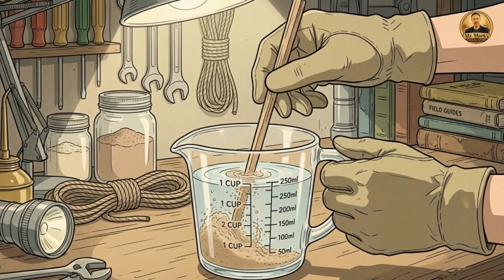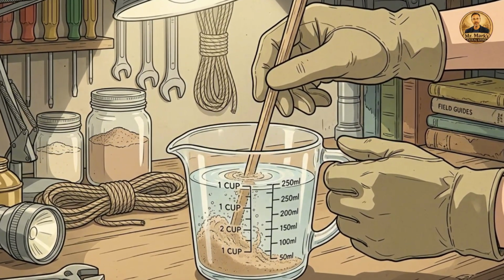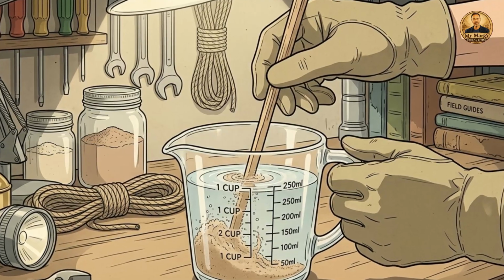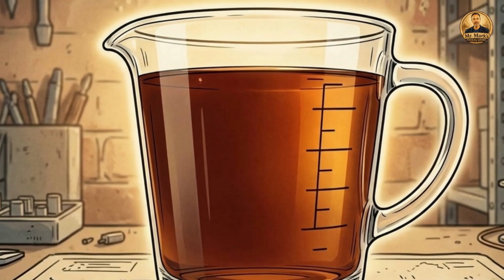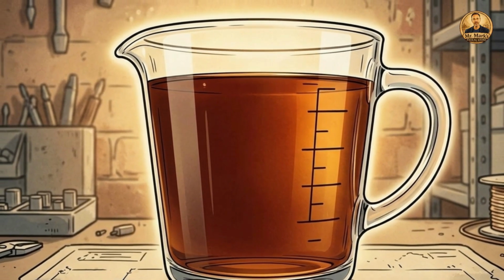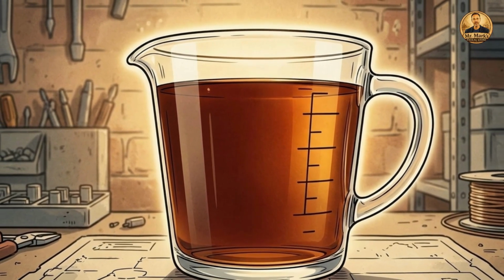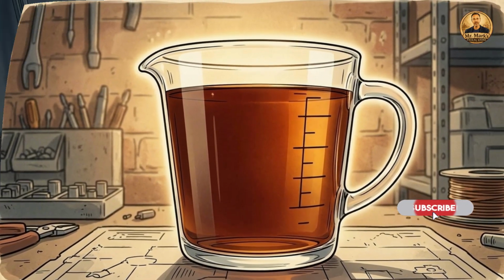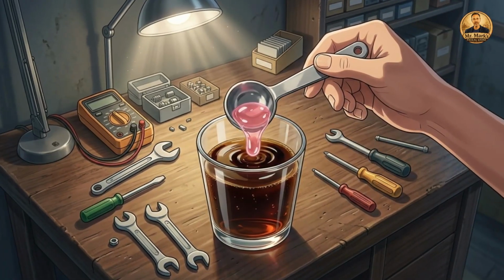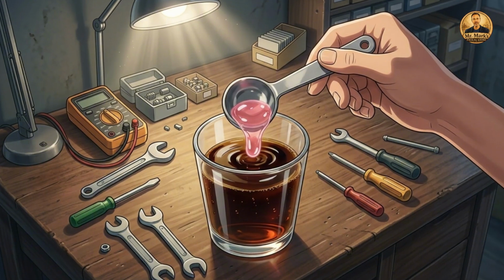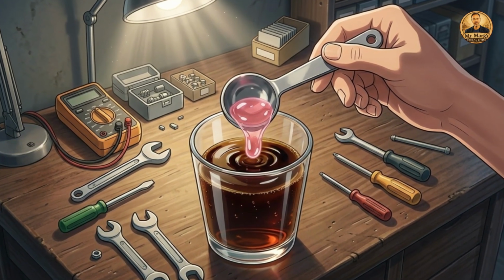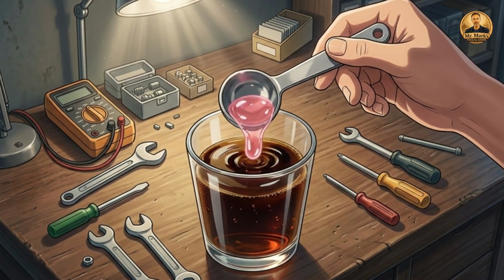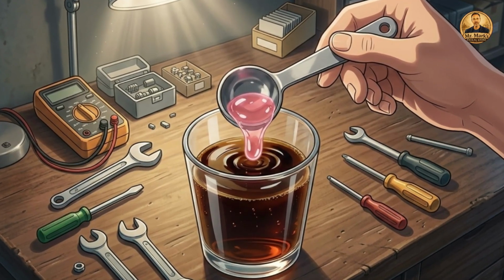Mix 4 grams of tannic acid powder into 100 milliliters of warm distilled water. Stir it until it dissolves completely. The solution turns the color of strong black tea. Then add 1 teaspoon of naval jelly and stir that in. The phosphoric acid does 2 things. It drops the pH of the solution toward that optimal 2.2 range, and it converts any remaining iron oxyhydroxides into iron phosphate, which is equally stable and equally protective.